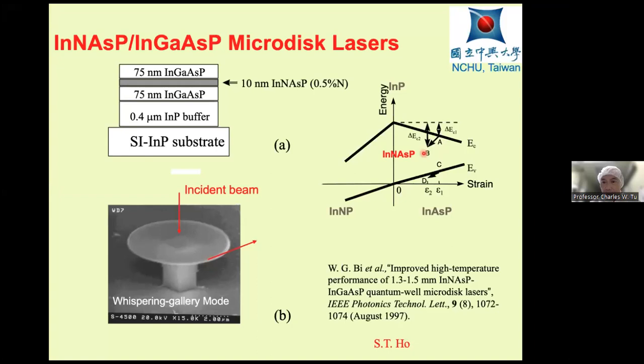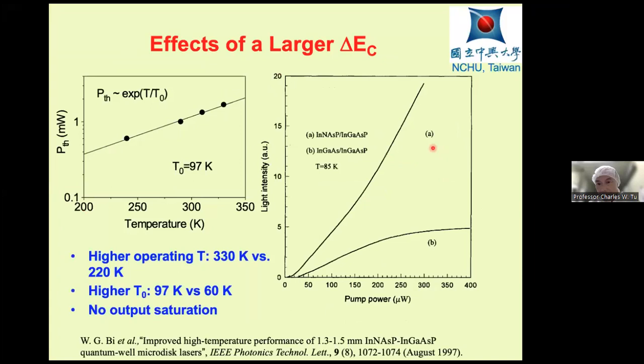And here I show how with incorporation of nitrogen, delta EC is increased. Okay. And as a result, we have higher temperature operation. So this is an indium gallium arsenide phosphide quantum well, and we compare with a dilute nitride quantum well. And you see the indium gallium arsenide phosphide quantum well saturates. Okay. But here, there is no saturation. And the operating temperature for this one is 220 degrees Kelvin, and for this one is 330 degrees Kelvin.